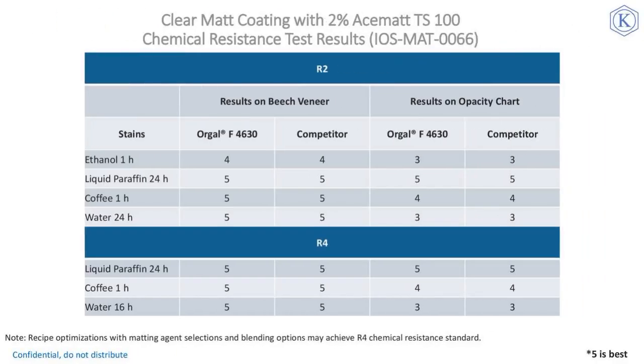How about again on black and white Leneta, and how is the performance now for IKEA approval, IKEA grading? As we see, R2 was not achieved in the gloss formulation. Of course, a similar picture applies for the matte one. Here with silica, R4 is also not achieved due to the water resistance at 16 hours, which is 3.